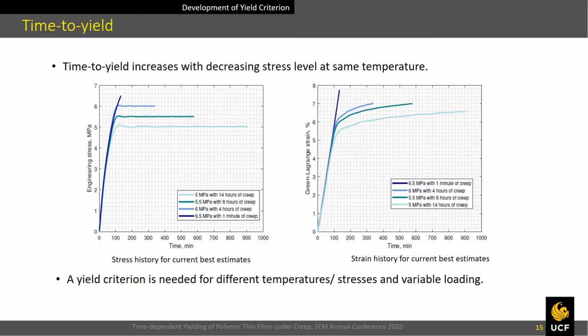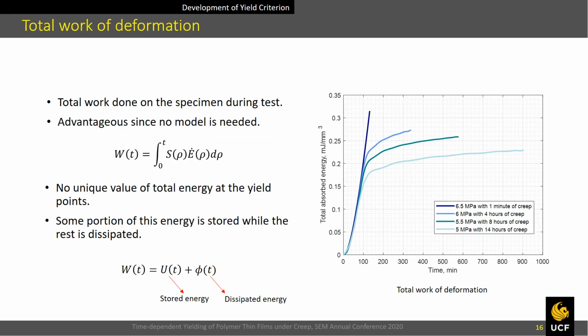A yield criterion is needed for different temperatures and stresses, and also for variable loading histories. The objective is to determine a yield criterion that can be used for varying temperatures and stress history. Therefore, 2 criteria employing energy are investigated. The first one is total work of deformation during the test. It is simply the area under the stress-strain graph. It can be advantageous since no model is required.